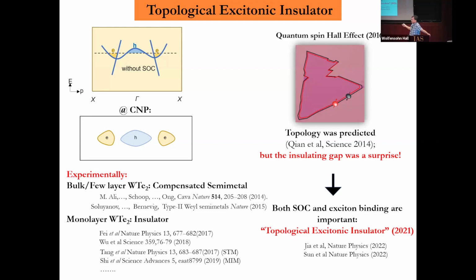Around the same time we started working on the experiment, and we spent several years confirming that it is indeed a quantum spin Hall insulator, and that the bulk is insulating. The theory initially did not predict that the gap exists, but experimentally it's gapped - a very happy ending. You have topology from theory and an insulating gap in the middle. So we checked all these properties of the quantum spin Hall state, and it does exist.